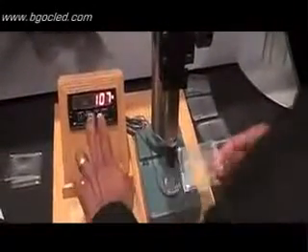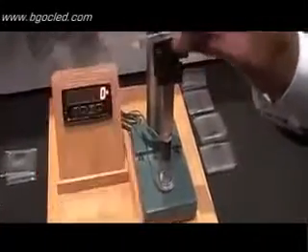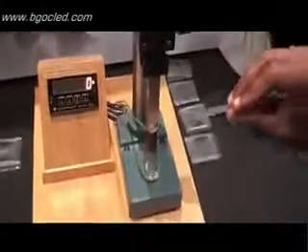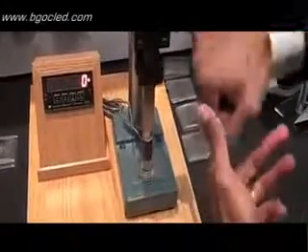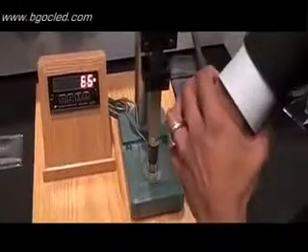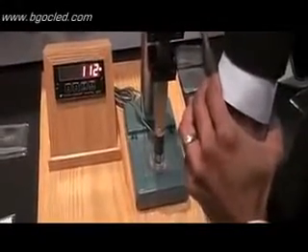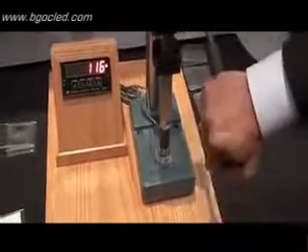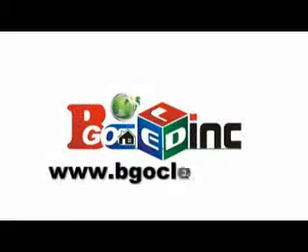We'll test that out with this lever press. Here we're at 0.8 millimeters — you can see the glass is much thinner than what's over here. We'll put that in here and test that. 116 pounds. The glass doesn't break. That's Gorilla Glass 2.